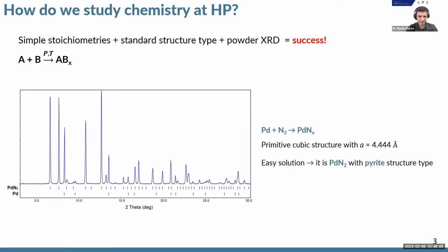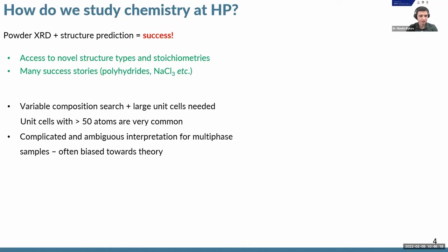However, this simple case is actually quite rare in what we do at very high pressures. Sometimes we get something really unexpected, and we get multiphase products. In this case, a very powerful method is to use experimental powder X-ray diffraction plus evolutionary structure prediction algorithms, which give us candidate structures. Then we compare the powder patterns of these simulated structures with the experimental one, and choose the one which fits best. This approach has resulted in many success stories and really allows us to get novel structure types and stoichiometries.